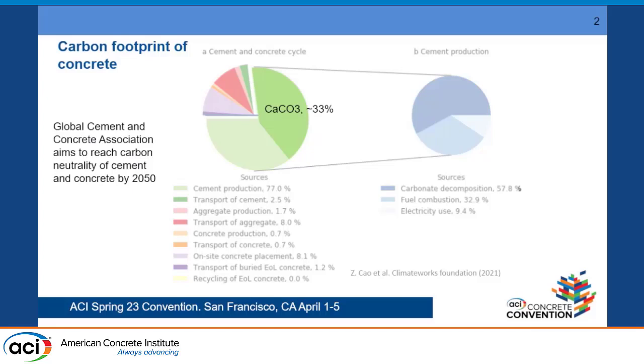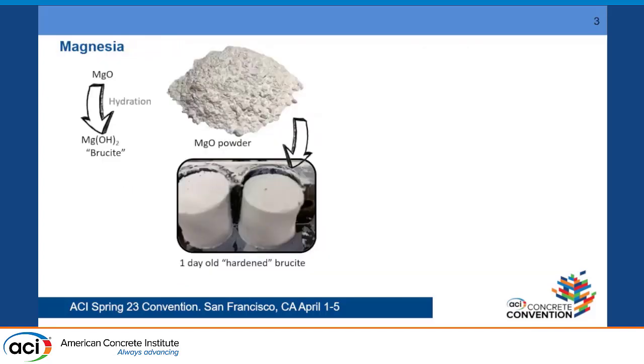So one of the questions that I wanted to answer is, can we go a step further? Can we start to talk about carbon negative concrete? For that, we have to forego the calcium base and look into another mineral, and that is where magnesia comes from. Now, magnesia or magnesium oxide is not novel. It's actually been used for at least 150 years. It's part of almost every cement batch. Typically, it's used at 1%, and in some large structures, we use it at 5%.